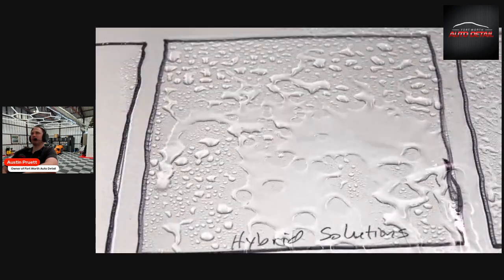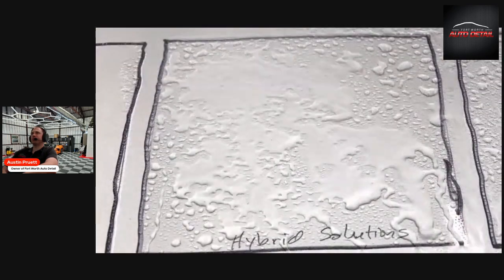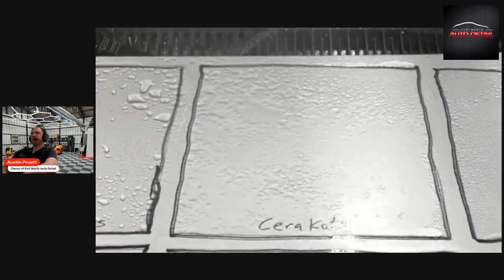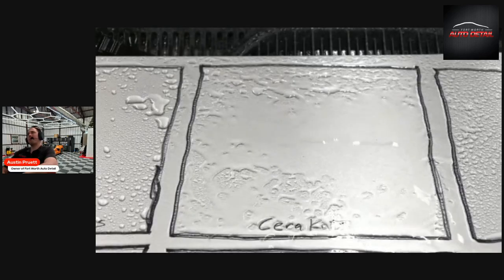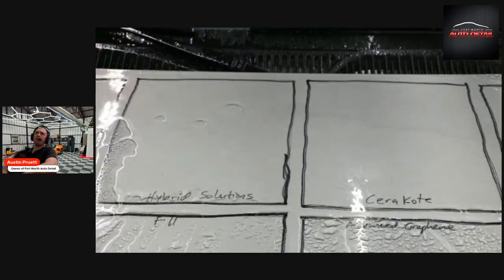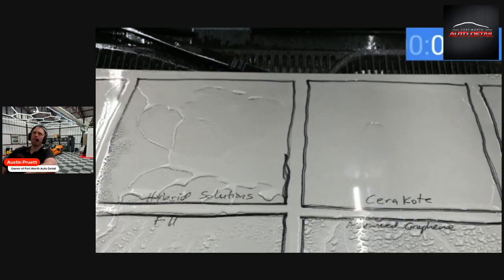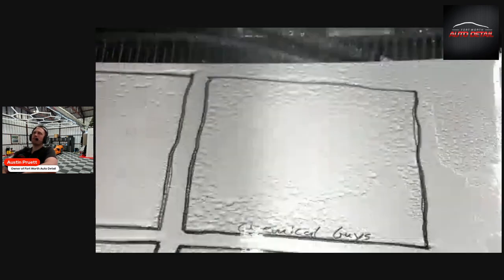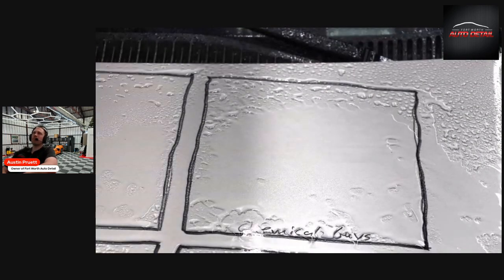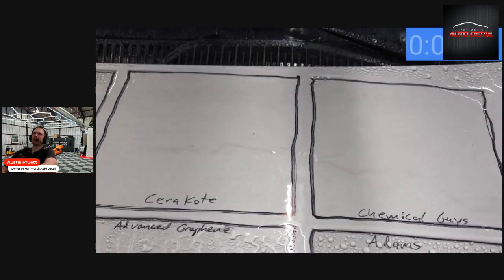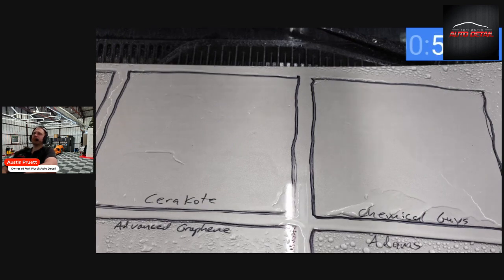And the bug and tar remover definitely did some damage to the hybrid solutions, but water is still beading. The bug and tar remover seems to have caused more damage to the Cerakote. With a heavy water spray, it took 15 seconds for the sheet of water to dissipate with the hybrid solutions. The Chemical Guys also experienced a lot of damage. With a heavy spray, a sheet of water quickly formed. The Cerakote and Chemical Guys needed a full minute for the water to dissipate.